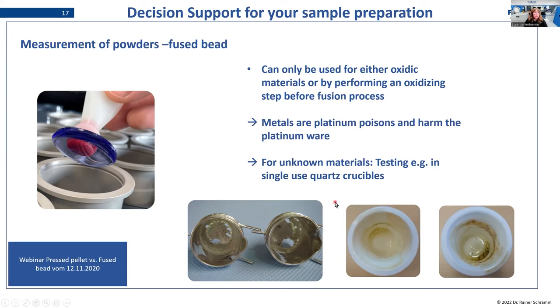So as I said in the very beginning, for the visual check, it makes sense to have a look if you can already see metal particles. If you're not sure about your material, it makes sense to test before if there's metal particles in there. You can, for example, do it like we do it. We are taking these quartz crucibles. You can use an adapter to fit them into the electrical fusion machine. And you just prepare the sample as you would in the platinum ware, but you don't pour after the fusion process. So you can obtain and have a look onto the melt inside this crucible. And you can see in this case there, we are having a lot of metal particles and here we don't. So this one would be okay to fuse in platinum, this one better not.